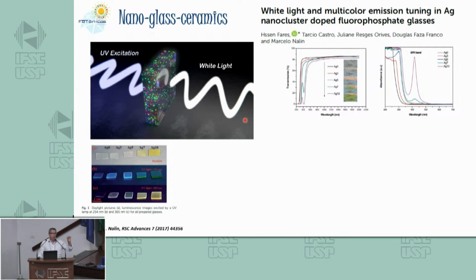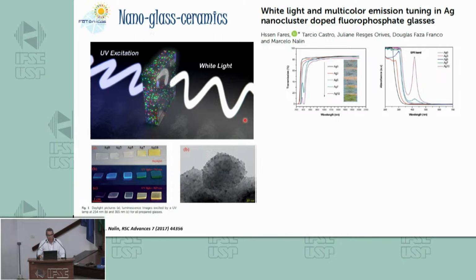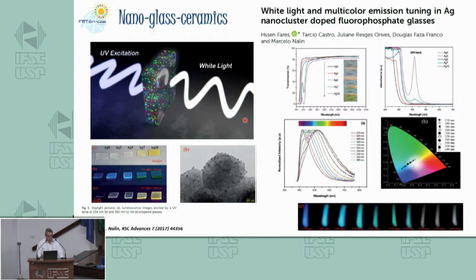And before becoming a crystal, we have some nuclei, okay? And depending on the size of the nuclei, the emission of silver will be different in the visible range. So if you can control the size of the nuclei before having a real particle with a nanometer size, we can in fact have different emissions. In this case, we could tune from blue to white.